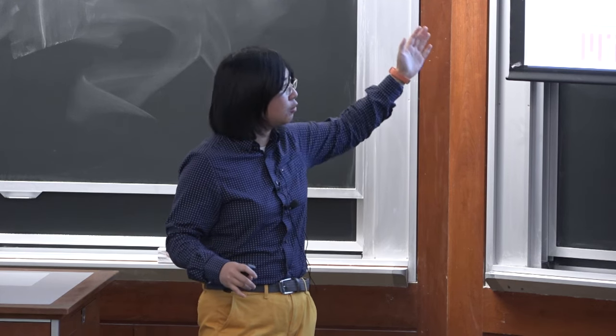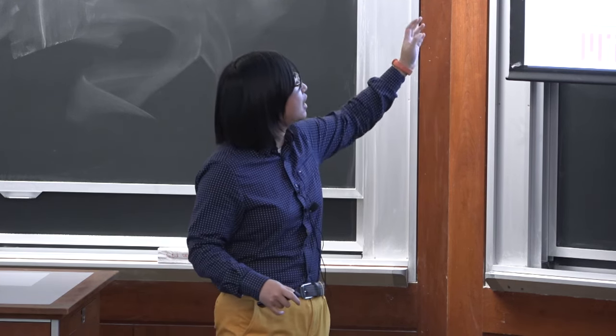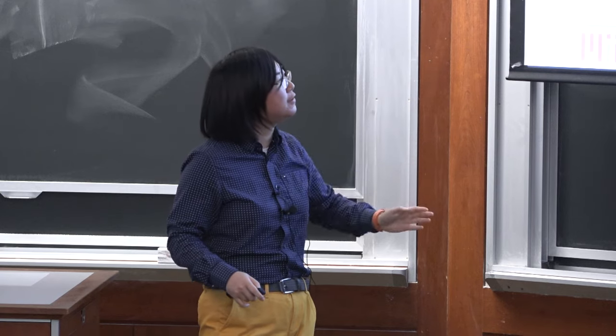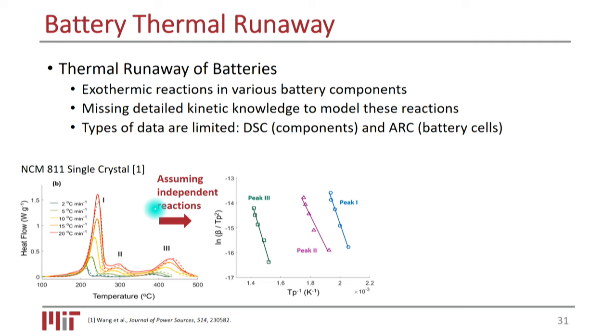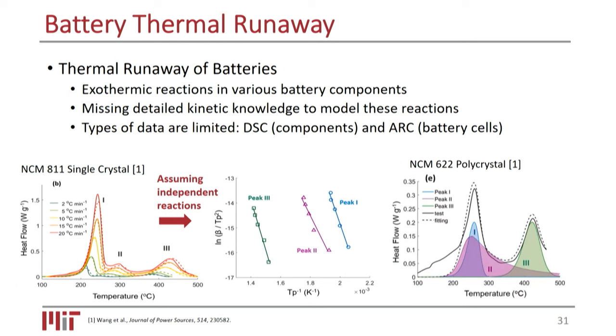And the peak location, we can take that and compare how the peak location shifts as we change the heating rate. We can come up with a figure in the middle. And then take the slope of that figure and it will give us the activation energy. And this works pretty well. Well, at least it looks like it's working pretty well for a system like this where we have three distinct peaks. However, what if you see a figure looking like this?